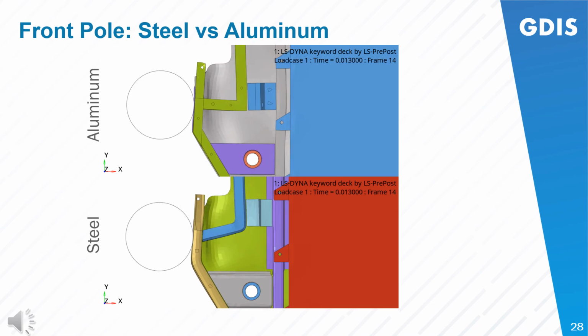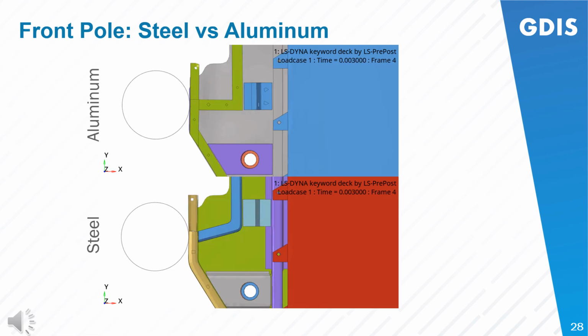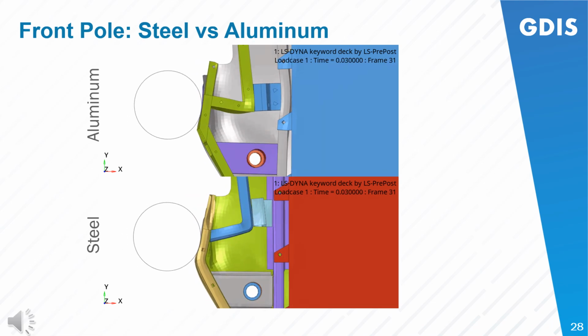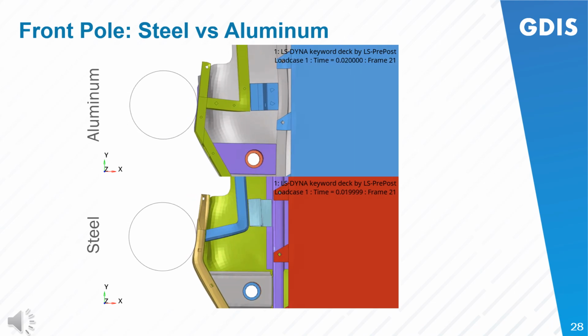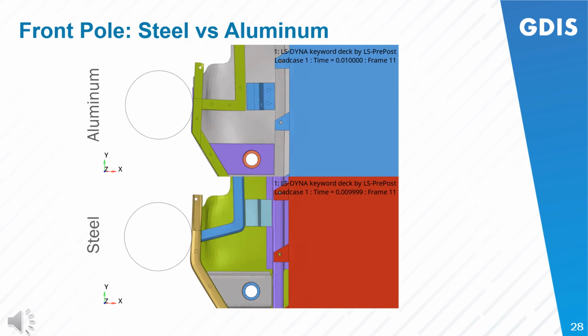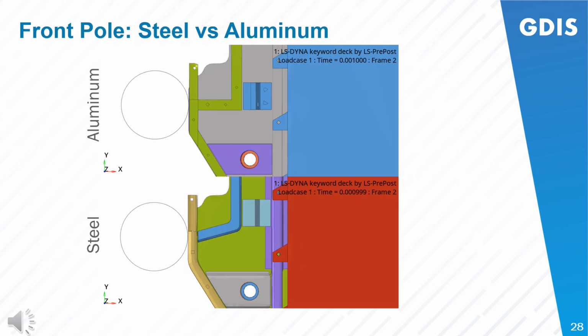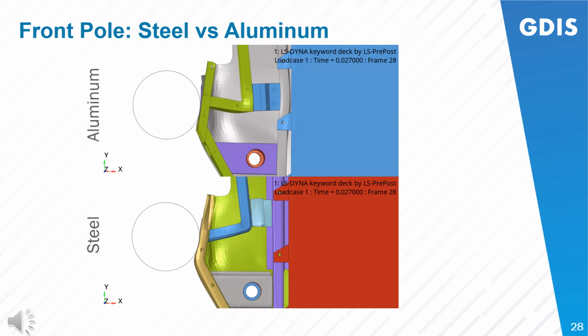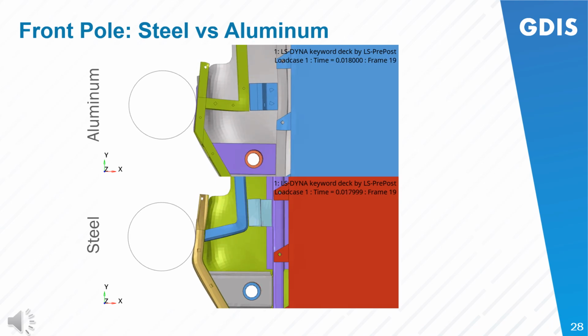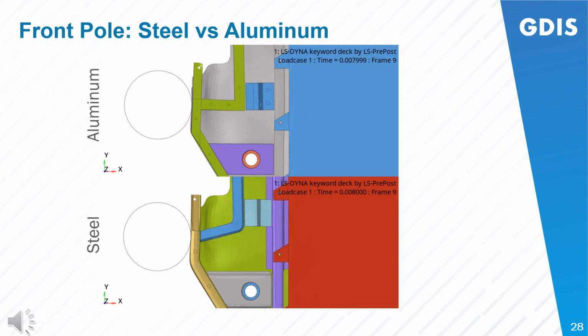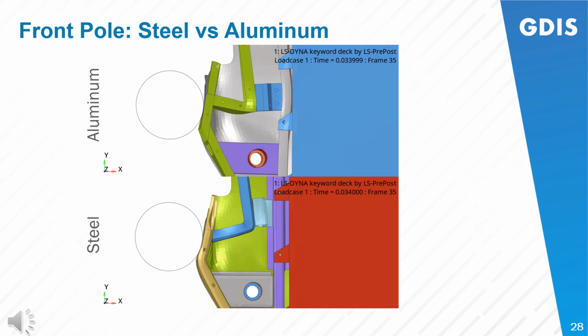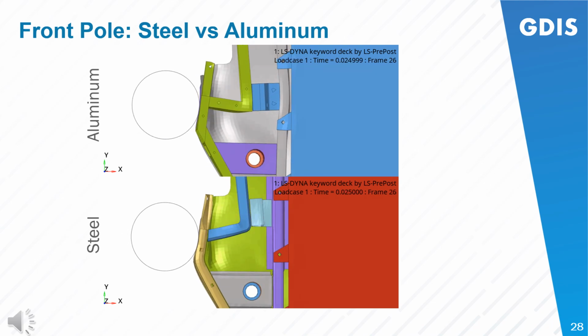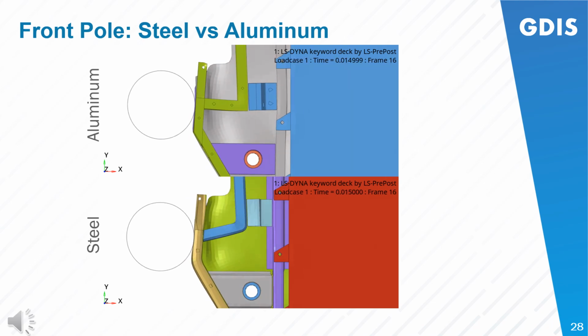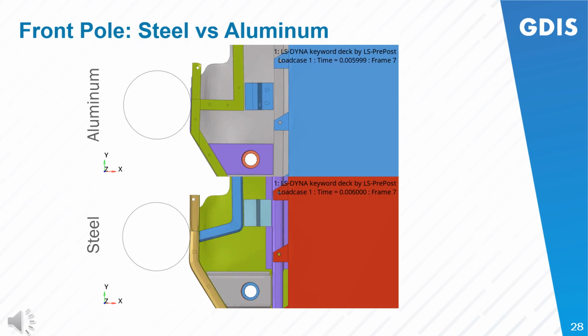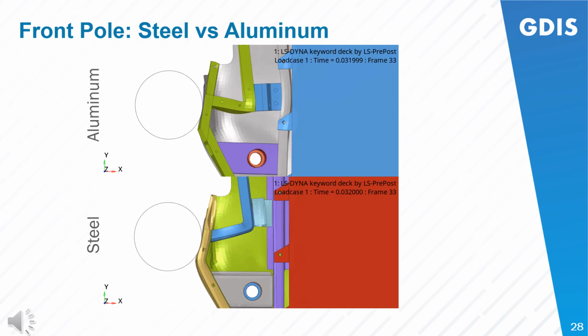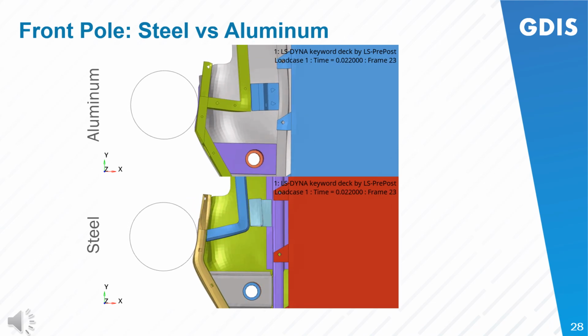So to that point, if you look at both performances, you'd see that the aluminum crossmember, which is shown in gray ahead of the modules that are shown in blue, is deforming a little bit. It's kind of bending because it's being pushed by a fairly strong bracket, while in the case of the steel, the modules that are shown in dark red behind the martensitic purple crossmember, the purple crossmember is hardly bending because the bracket and the structure ahead of it are actually absorbing energy.